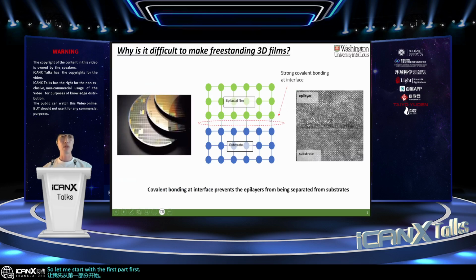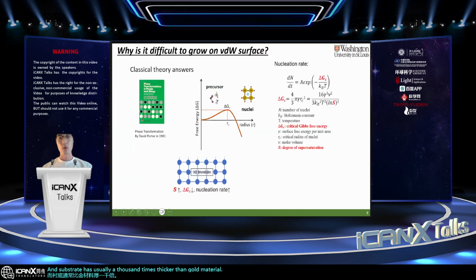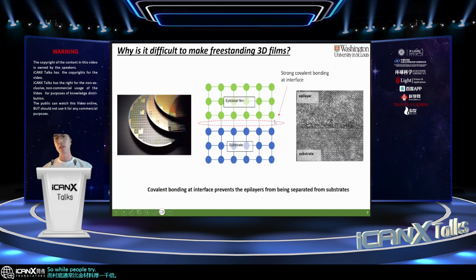We need to look at why it was so difficult to make a very thin freestanding 3D membrane. That is mainly because the problem comes from the strong covalent bonding at the interface. Because of this strong covalent bonding, we cannot easily and selectively separate the grown material from the substrate. And the substrate is usually 1,000 times thicker than the grown material.